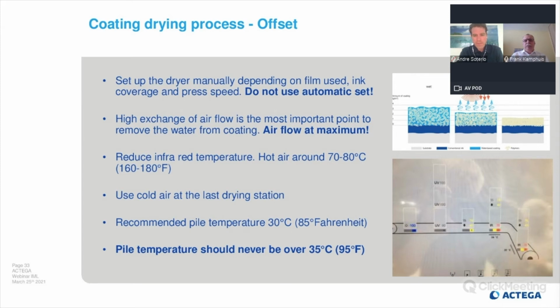That means dry air comes into the system and wet air leaves the system. And practice shows that you have to adjust the hot air between 160 and 180 Fahrenheit, if possible, and you have a cooling air at the end of your station. That is an advantage. Then please check your pile. So pile temperature should not increase over 85 Fahrenheit. So please check it and never use more than 95 Fahrenheit.